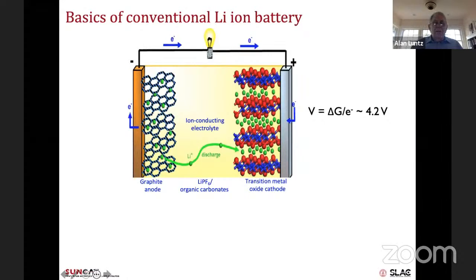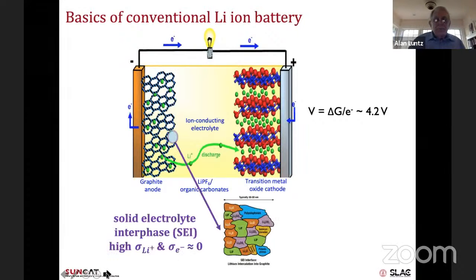But there's another very important part to that battery, which is the solid electrolyte interphase. Because the anode is at such a low potential, just slightly above lithium metal, it reduces the electrolyte. It continually reduces the electrolyte as long as it can. And so the interface is just a mixture of these reduced compounds, a whole series of inorganic and organic materials that plate out on the anode particles. And ultimately, if they have a low enough electronic conductivity, this reduction and consumption of the electrolyte stops.